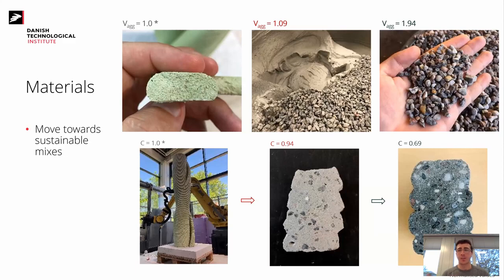I'm not saying that the mortars will not compete. There are applications where pre-mixed mortars and custom mixed designs of mortars are necessary, because that gives you a nice small feature resolution of what you're printing. When you're working with concrete, in our case with 8 millimeter aggregates, then your minimum resolution during a print becomes 8 millimeters. There's a lot of difference. It's like getting a beautiful fine printer, and now you're making really chubby thick layers, and they look okay from a distance, but when you come closer, you lose the sense of it. It's more architectural. Probably one of my colleagues, Thomas, who is an architect, would have a more technical comment on that.